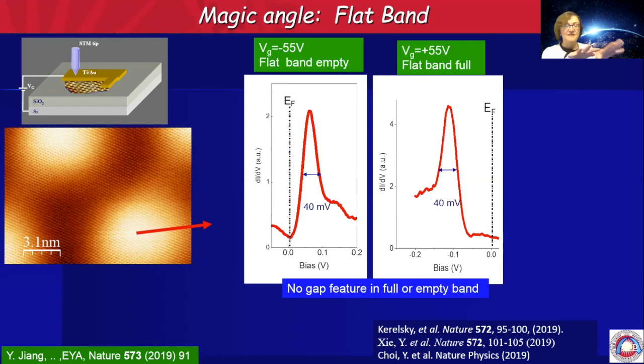We have many twist angles on this sample. We could go and search for the region where the band is narrowest, where the two Van Hove singularities have really merged. And this is where we found it. So now we gate the sample to put the Fermi energy outside of the flat band. So this is undoped. And you see we have this nice flat band. Then we gate it and we move the Fermi energy to the other side. The band is pretty much unaffected. And now we're taking the Fermi energy and putting it smack inside the flat band.